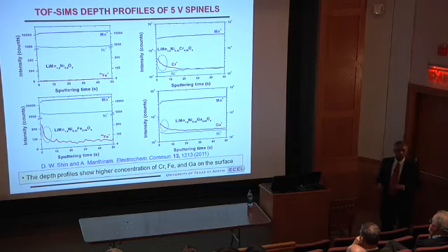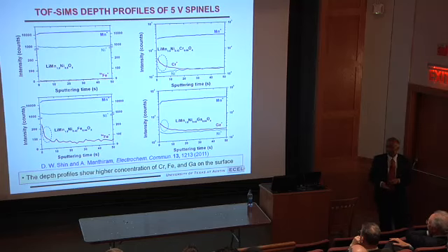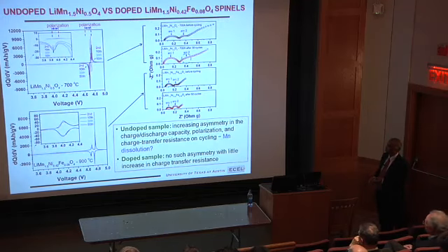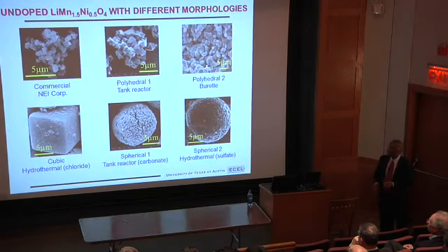So this is one-step synthesis. You are not coating externally. During synthesis, certain things segregate by themselves to the surface, and the surface is enriched with certain friendlier ions. That's why they show better performance. I think that's also reflected in the impedance.